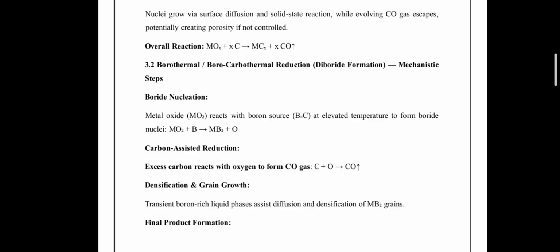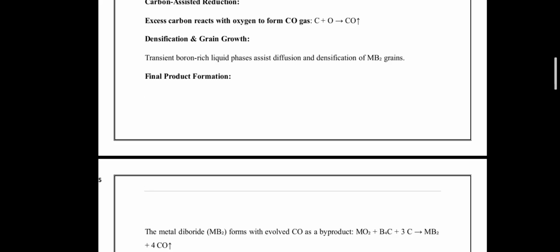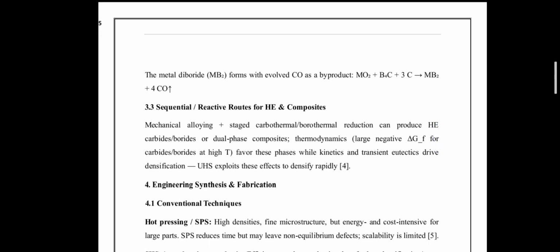At high temperature, a transient boron-rich liquid phase may form, significantly enhancing mass transport. This liquid promotes rapid diffusion, grain rearrangement, and densification of the diboride phase. The final result is dense MB2 grains with carbon monoxide as the primary gaseous byproduct. The overall reaction is metal oxide plus boron carbide plus carbon, giving the metal diboride, with carbon monoxide eliminated as a byproduct. This pathway explains why diboride processing is more sensitive to carbon balance and temperature control than carbide synthesis.